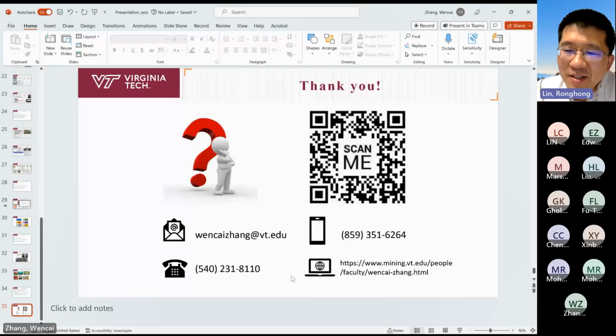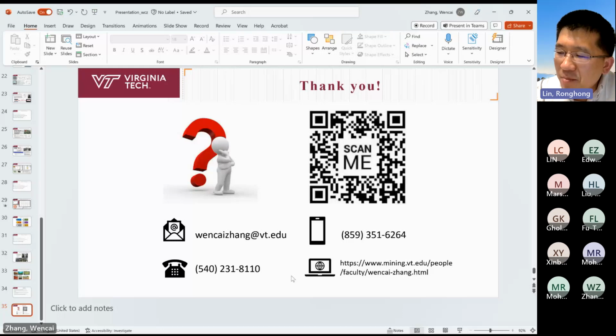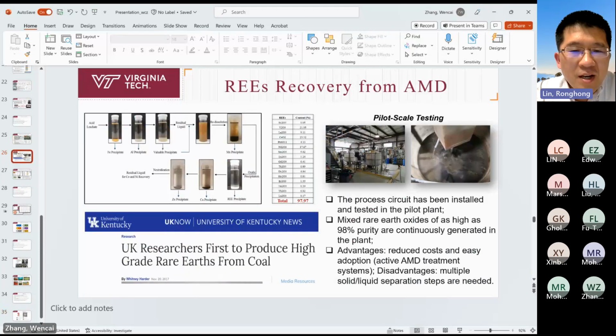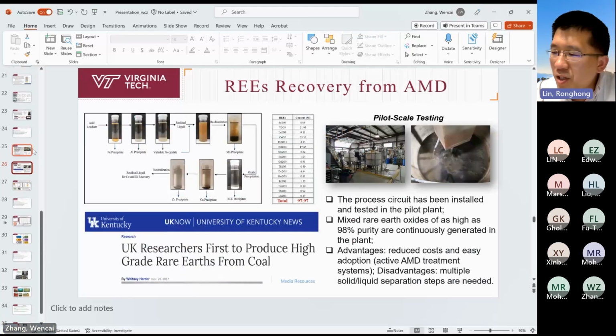So I have a question. About the AMD, you showed a very exciting achievement that can enrich the rare earth element from ppm level to about 98%. That was just amazing. My question is what is the recovery? You have very high concentration purity, but what's the recovery when you do the precipitation at pH level around 7? Yeah, the recovery is also high.